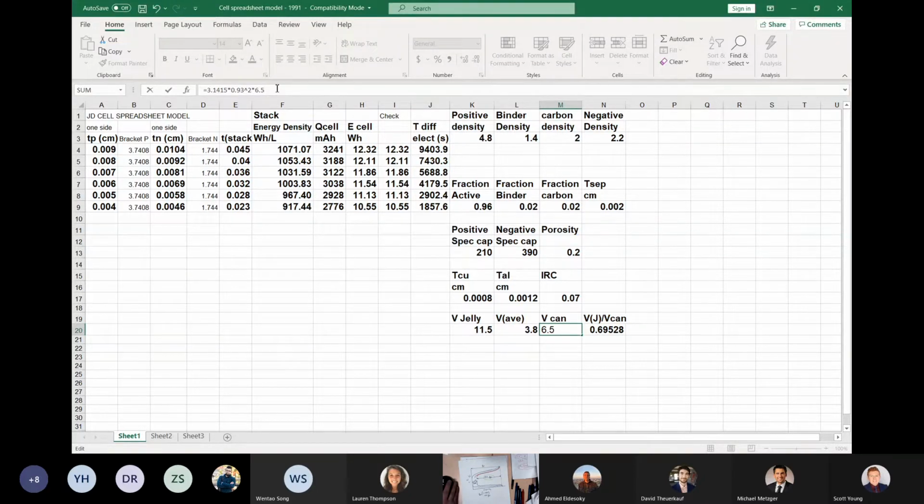And why won't that enter? That gives you 17.6, which means to get our 70% filling, we can go up here to about 12.5. There we are. And now we're at 3,500 milliamp hours in the cell. So these are the tricks that you play. You just keep jamming more stuff in the can. You cheat on the can diameter, and you end up with close to the 4 amp hour mark.